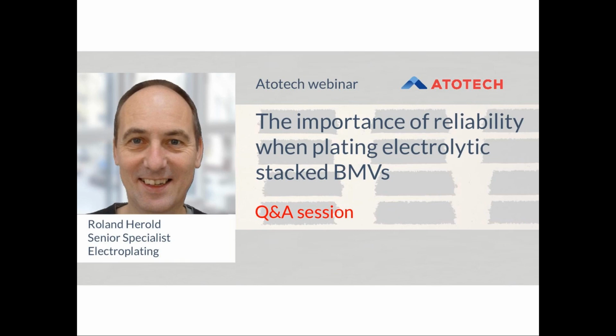Yes, so there have been several studies about the co-deposition of additives, plating additives, by increasing TOC. These studies have been also published by several institutes. In general, you can say if the TOC increase is caused by the plating additives themselves, you do not have to expect more adsorption of plating additives, because the breakdown of plating additives usually do not contribute to an increased adsorption of additives in the plated copper deposit.